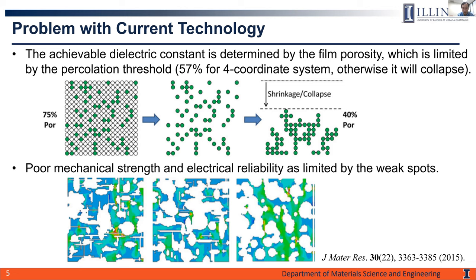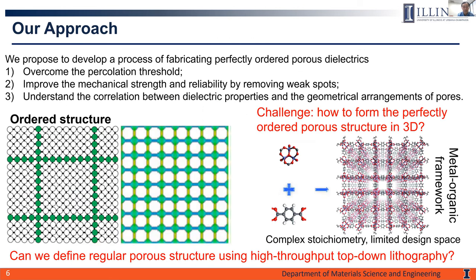But for these random pore structures, the further increase of the porosity level will inevitably lead to more prevalence of certain weak spots in the material structure, as shown in the simulation. Those weak spots will limit both the mechanical strength and the electrical reliability of the thin film. So then the question is how we will be able to overcome these limitations.